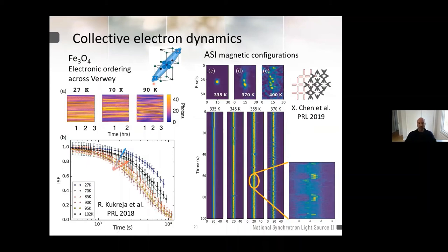which has a certain relevance with some electronic models that have been proposed. And also you can move to, let's say, engineered structures, not only working in bulk or thin films, real materials, but you can go for artificial spin ices, for example, and check the magnetic configuration in a square lattice, as was chosen in this case, where you clearly see that you work at a much more comfortable temperature, because being engineered, you can do almost what you want in terms of amount of materials, symmetry, topology, interaction by distance, and so on and so forth. So you can tune the sample really almost as you want.